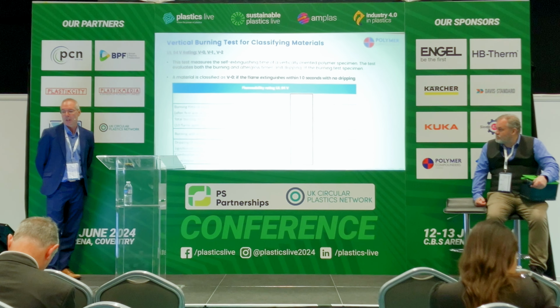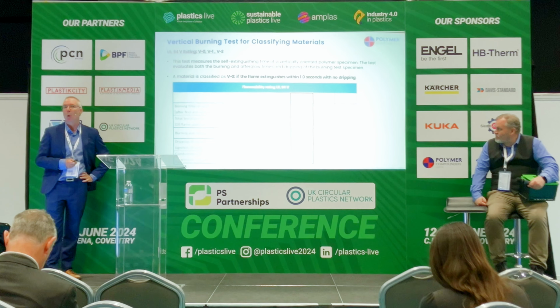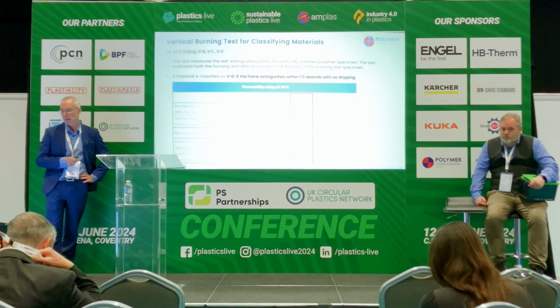Just to clarify, for injection molding and extrusion, the most common flame retardancy rating that we'd be looking for is V0 UL94 test. The flame is going to extinguish within 10 seconds and there can be no burning drip. So that's really what we're trying to achieve with any new flame retardancy development.